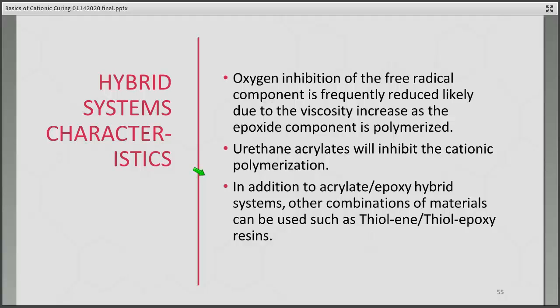Oxygen inhibition of the free radical system's component is frequently reduced. And this is likely due to the viscosity increase as the epoxide component is polymerized. So you delay that glass state, and you tend to get a little bit further reaction, and you get reduced oxygen inhibition. One thing to remember is that urethane acrylates will inhibit the cationic polymerization in hybrid systems because of the urethane functionality there. They will react with your acid generated system and slow down or potentially kill your reaction. So you just have to steer away from urethane acrylates.